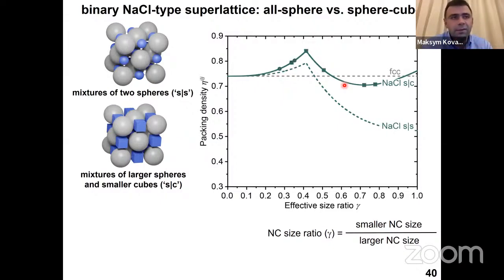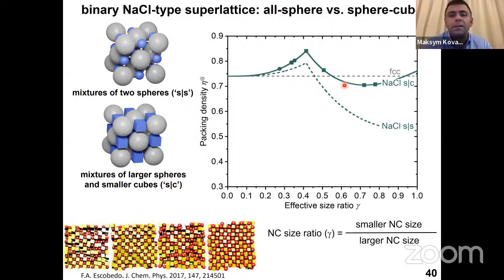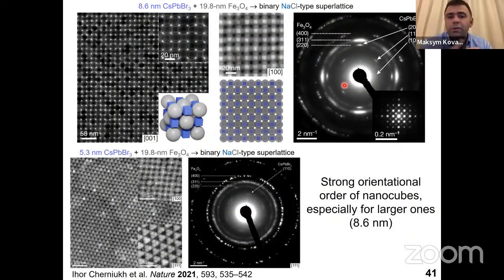And we tested this, and there were theoretical predictions that this is the case, even years before our work. And indeed, we observe a superlattice where the perovskite cube is surrounded by these spheres of iron oxide or another compound. In this case it's iron oxide, but it also can be some dielectric material.